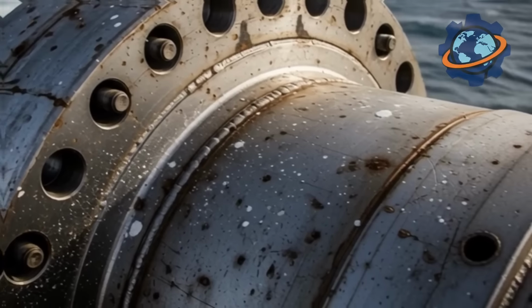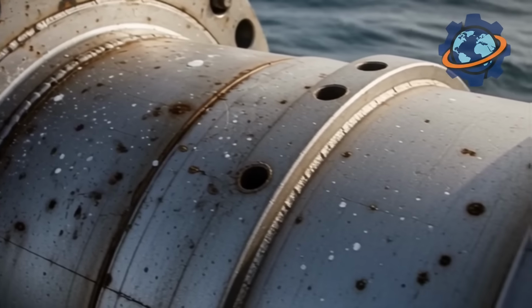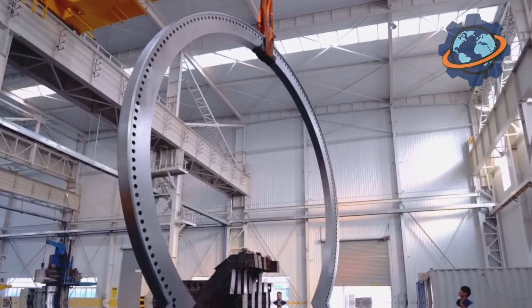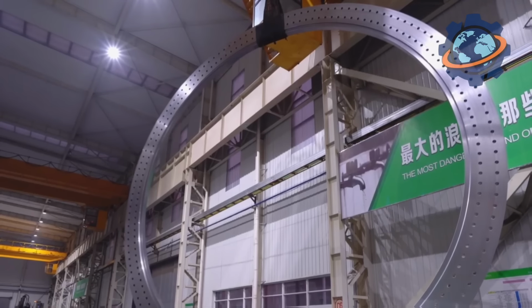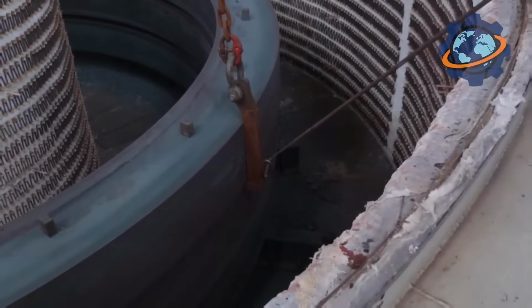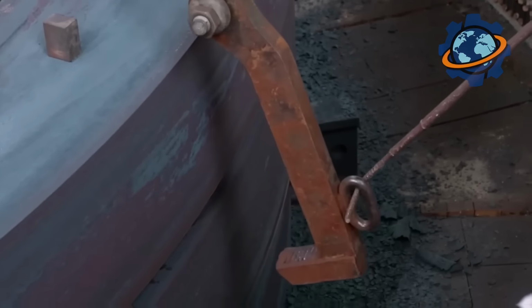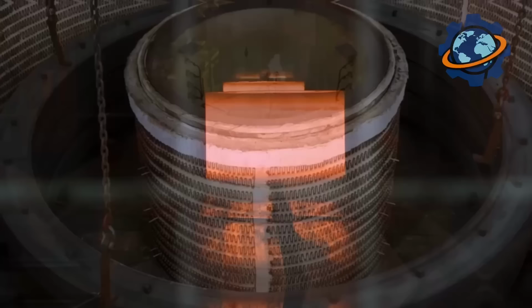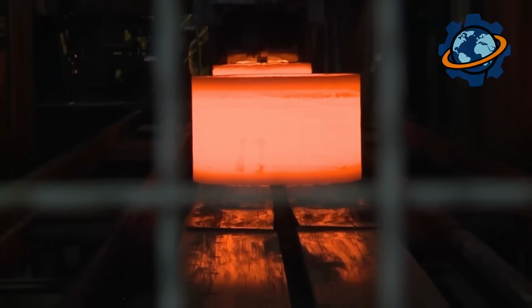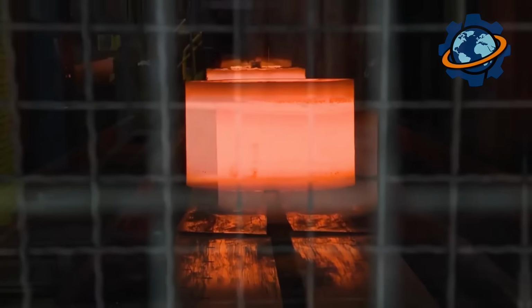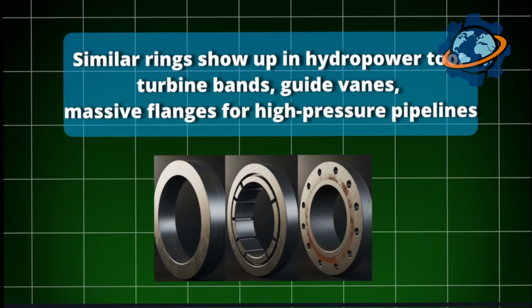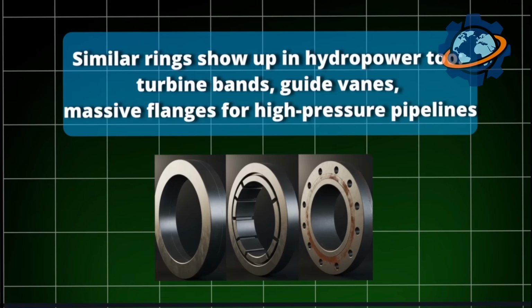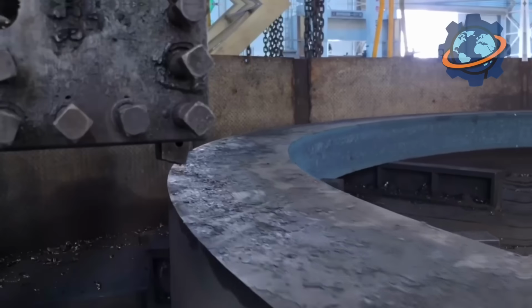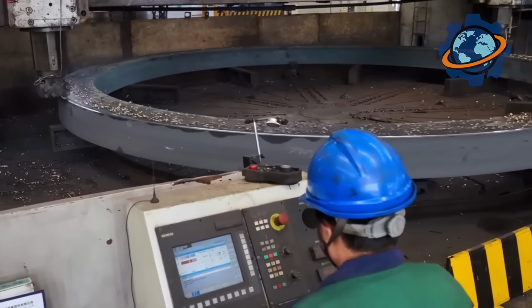Offshore wind farms need massive flanges and rings that can handle punishing wind loads, salt water, and constant fatigue cycling. Here, seamless rings have a clear edge over welded ones, thanks to lower cracking and deformation risks. Similar rings show up in hydropower too. Turbine bands, guide vanes, massive flanges for high-pressure pipelines. Anywhere a failed weld could spell disaster, manufacturers switch to giant one-piece forgings.